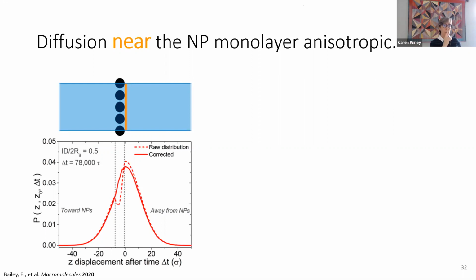There's your reminder. Now, if we do this for a layer of polymer that is right next to the particles, we see an anisotropy. So the raw data straight out of the simulation is the dashed line, with this dip here. And so originally we thought, okay, well, of course there's a dip, because the orange polymer here diffusing in here, there's a lot less space for it to go. So of course there's going to be this depression here, just because of the volume.